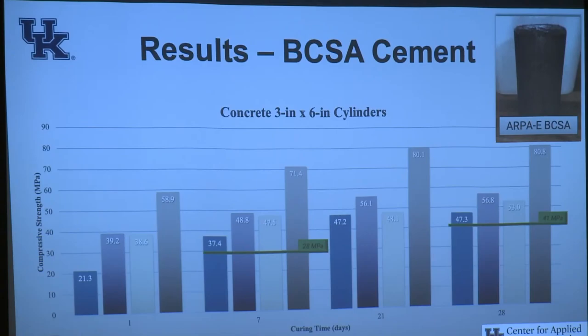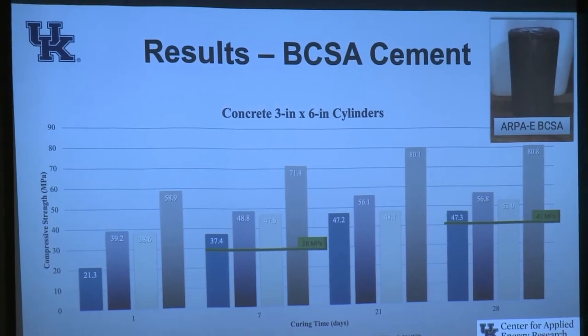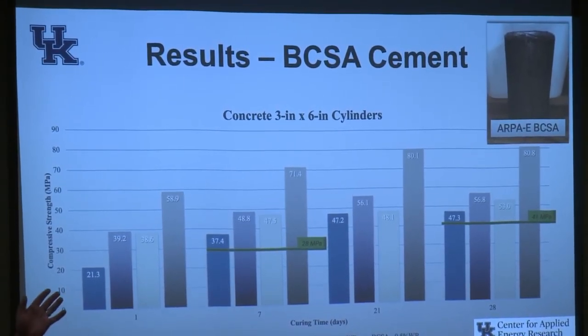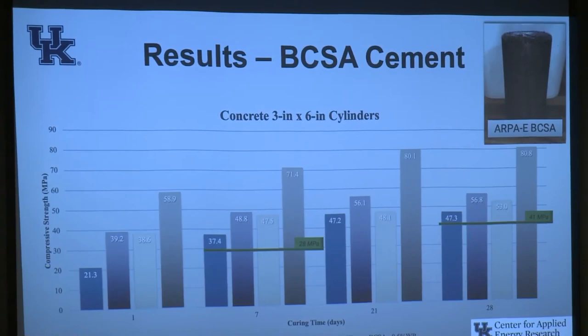Now here's the compressive strength of concrete cylinders, 3-inch by 6-inch cylinders. The light blue column on the far left, dark blue on the screen, is a Portland cement strength. 28 days is often the metric for compressive strength of concrete. And I apologize, this is in megapascals. That light blue one was designed for 6,000 PSI at 28 days. The next column over is a commercial CSA, calcium sulfoaluminate cement. You can see at day one, it gained a lot more strength than Portland. That's what it's supposed to do. But then they level out and run the same amount of strength gain.